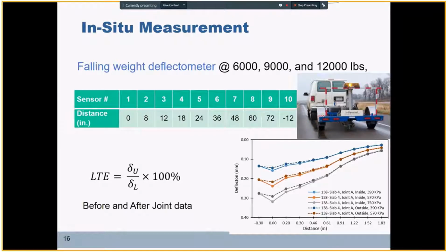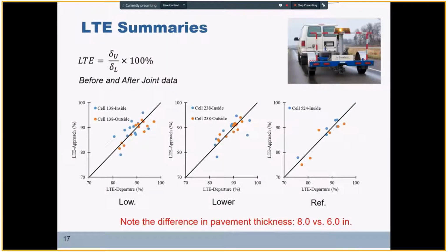We have used these data to calculate the load transfer efficiency on the joints in these two test cells. Here is a summary of the LTE data. For the experimental sections, cell 138 and cell 238, we have really comparable behavior in terms of LTE. The numbers range between 80-82% and reach as high as 97%, which are very good and comparable data for the departure and approach slabs for both cells, for both inside and outside lanes.